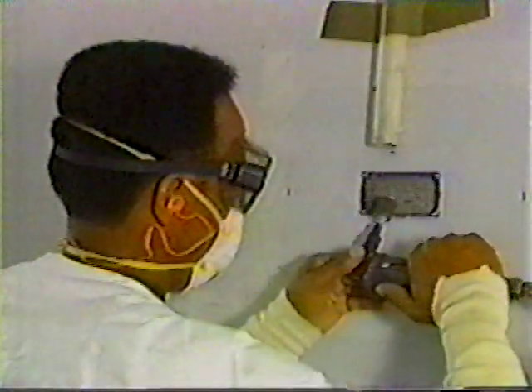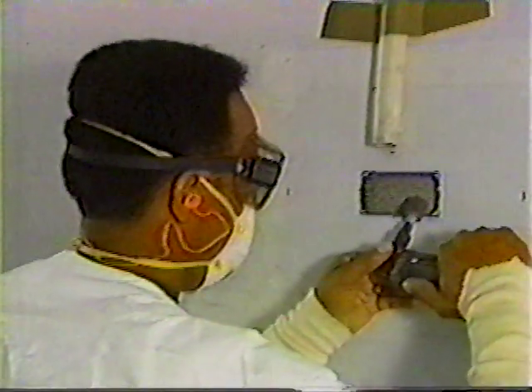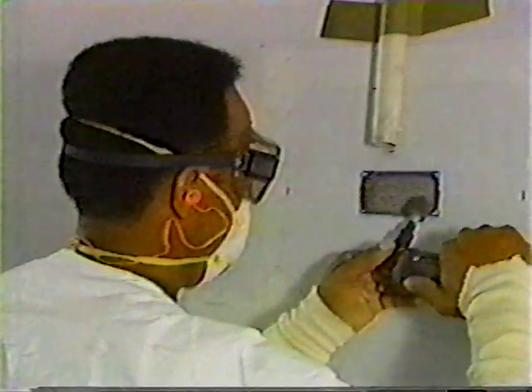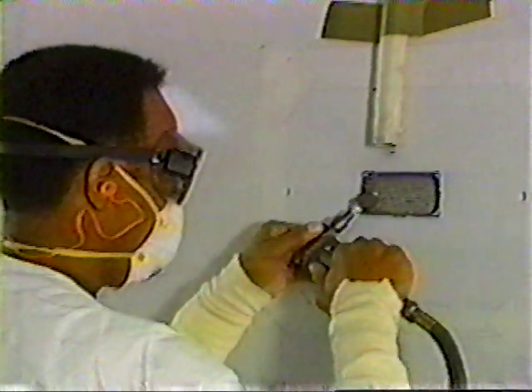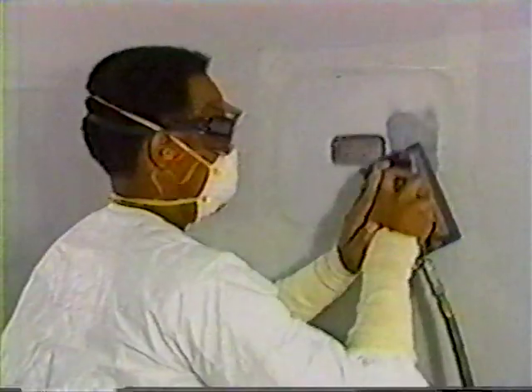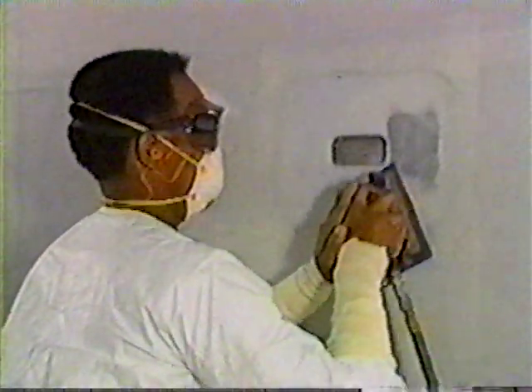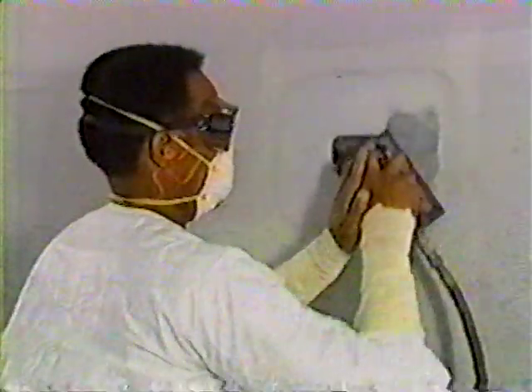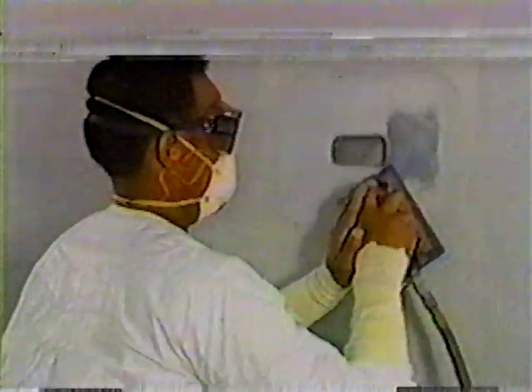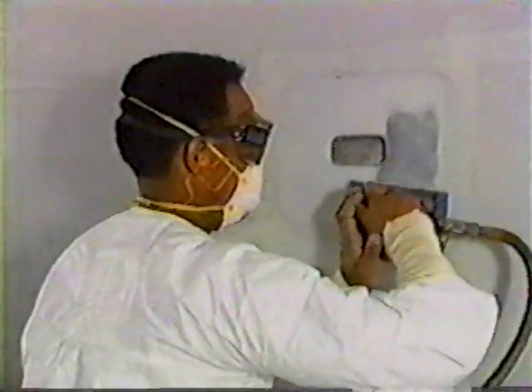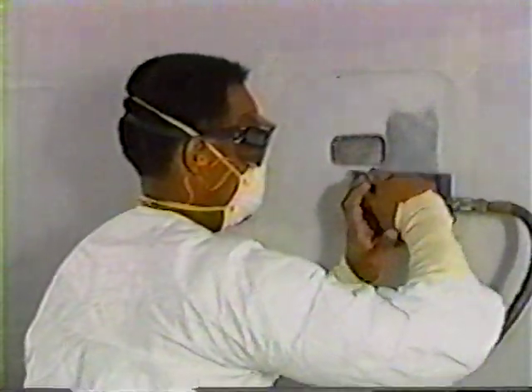Thoroughly vacuum the repair area, making sure all debris has been completely removed. Then, taper the sides of the cutout to form a 45-degree angle that opens outward. Next, abrade the top surface of the entire repair area with a 150 grit paper, making certain you do not break the graphite fibers on the top surface of the outer skin.